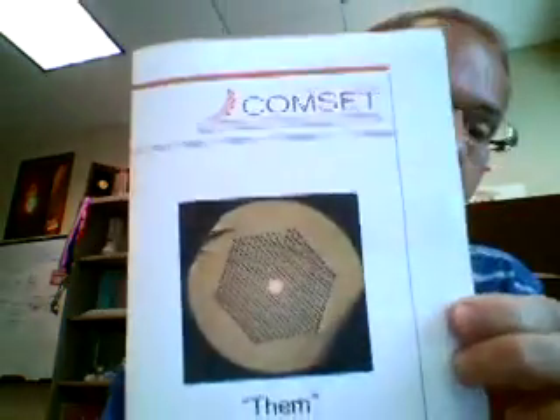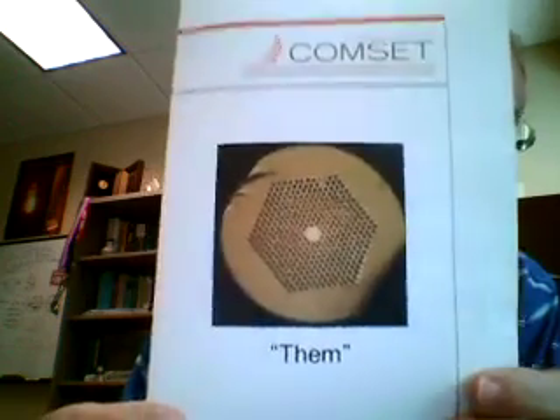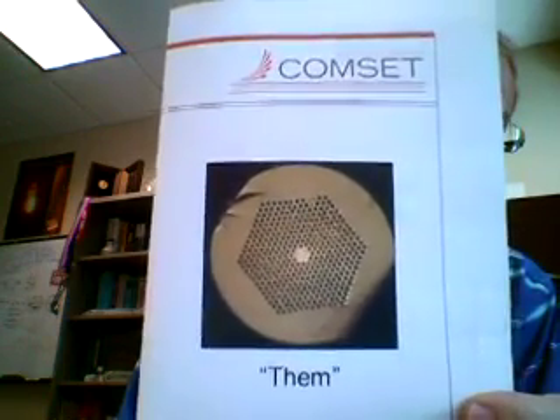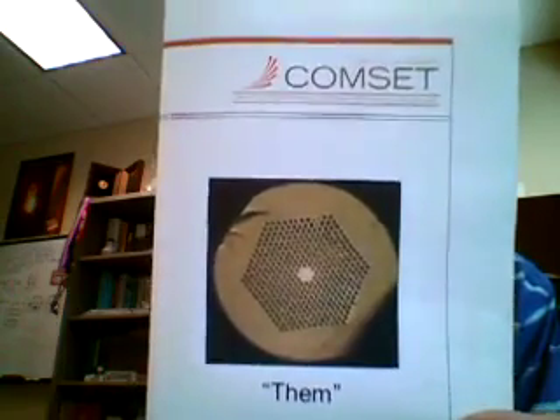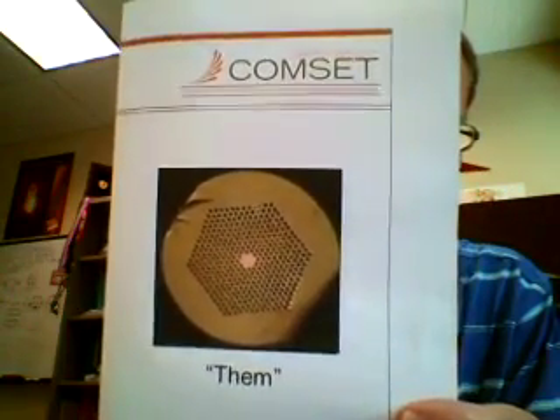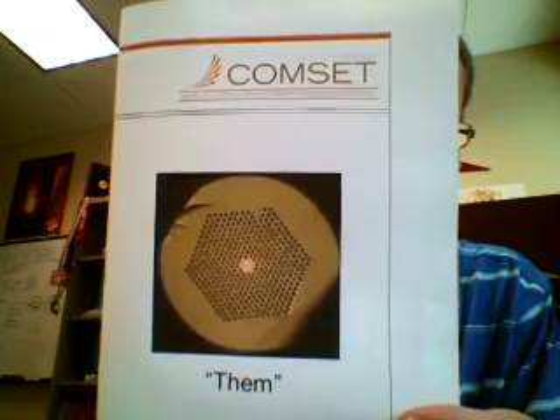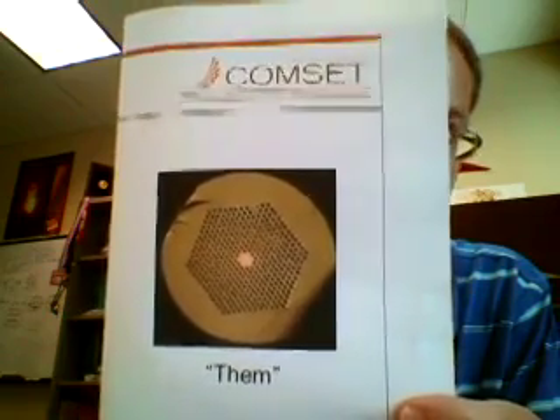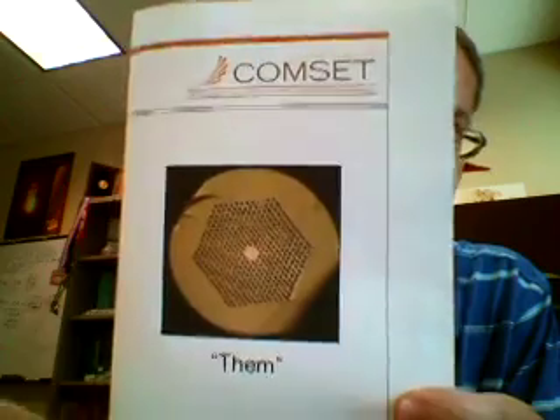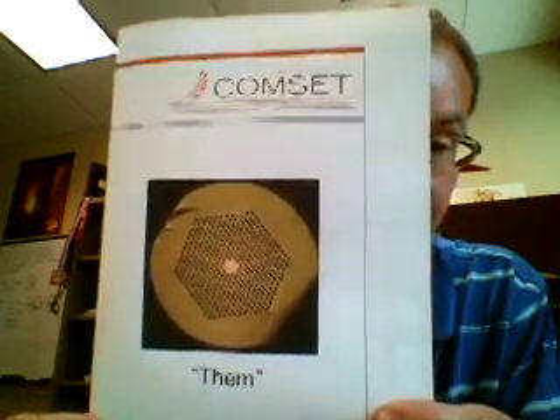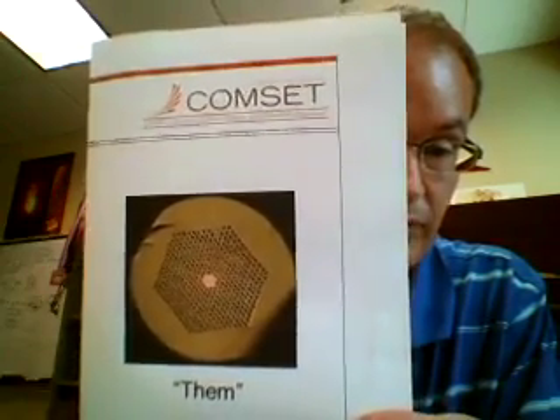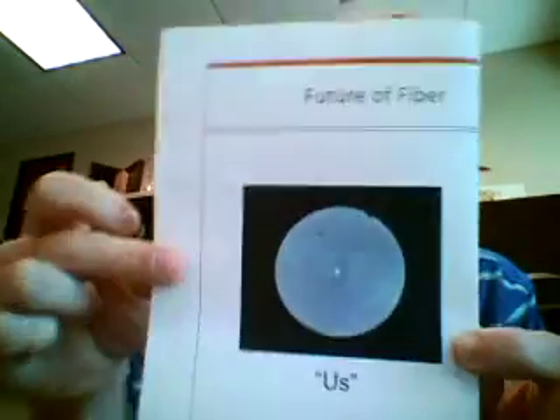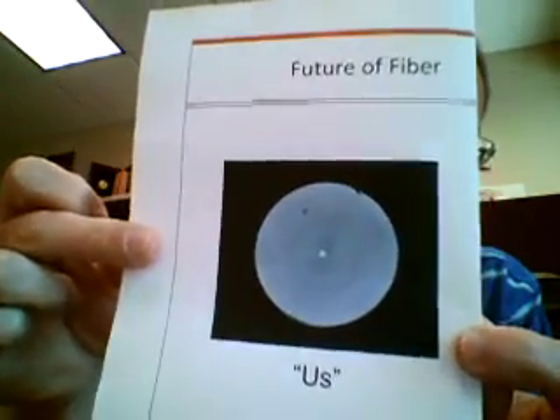The way that many people, again, are making fibers today looks like this. That's them, right? So they go to great lengths at stacking preforms and drawing them into extraordinarily complicated fibers, because they use the microstructure to influence the optical properties. The material, by and large, is all silica. So same material, but they use structure to influence properties. Our approach, though, is to use a new material and go to a much, much simpler structure.